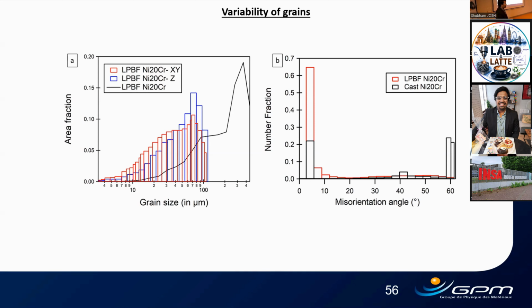So just on this slide, because I have another question regarding the grain size. You performed all your tests with the tensile axis along the building direction. Yes, all the tests. There is a slight difference on this specimen between the plane you are looking at for the grain size. For this energy density it's not so different, but I guess for the higher energy densities you should have a more pronounced morphological texture. Indeed. So which grain size do you take into consideration in your model?